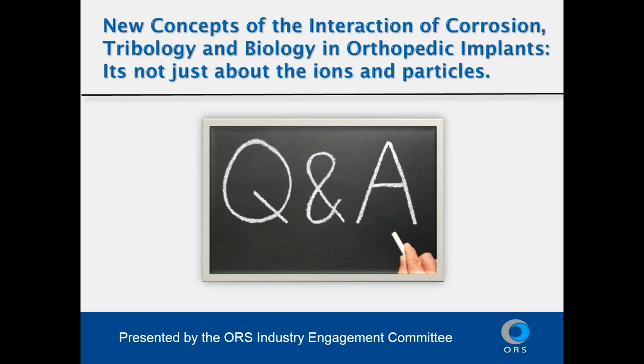Okay, so the next question, can you comment on crevice corrosion and crevice created by cell adhesion? Oh, well, that's a good question. So crevice corrosion, the mechanically assisted corrosion model that I've described does have an element of crevice corrosion associated with it in the modular tapers. And indeed, elements of the mechanically assisted crevice corrosion model rely on the fact that crevices can alter the solution chemistry dramatically and also create voltage conditions that are not conducive for maintaining the oxide film stability. The chemical changes that can occur include lowering the pH, increasing the chloride concentration, and depleting oxygen from the environment.